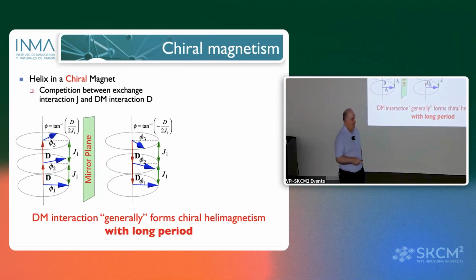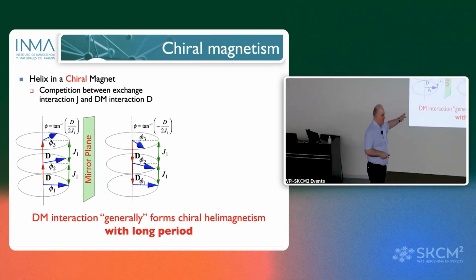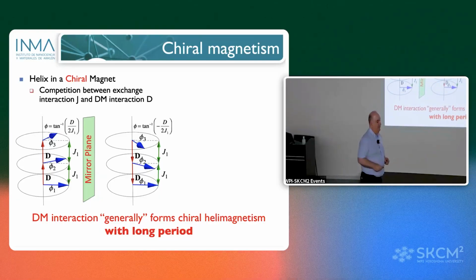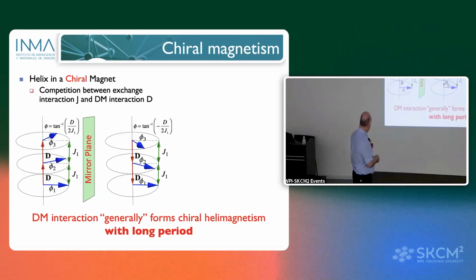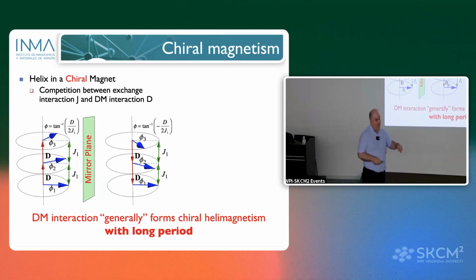Usually, what is happening is, in the crystal, because this is a magnetic structure, this is a magnetic enantiomer, one of each other, but in your crystal, you have domains from both chiralities. And then each nuclear domain will use one of these helices. If you have both nuclear chiralities, at the end you will have both magnetic enantiomers. But in the case you have only one crystal with only one hand, then you will observe only one helix propagating. We did experiments in the past, and we demonstrated that many chiral crystals are formed by chiral domains, and every chiral domain has only one helix of this. If you arrive to have only one enantiomer crystal, you will have only one of these.